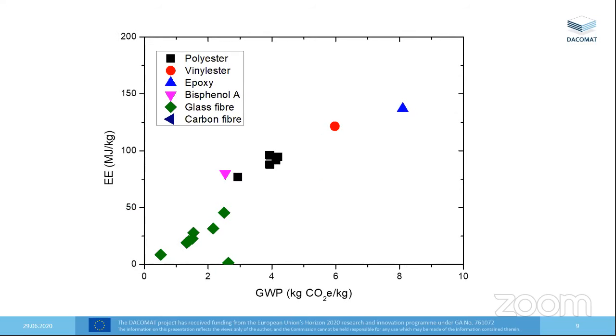So just to zoom in on part of this graph, we're now looking much more closely at the region that we're interested in from the point of view of the project. And what we're comparing here, if you look at the coloured triangles in the circle, are the resins, because one of the main things we're doing is altering the composition of the resin to see if that alters the fracture toughness of the composite, to see how it affects crack growth, crack development during the lifetime of a wind turbine blade.